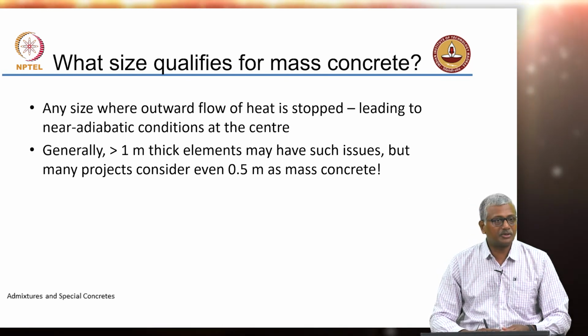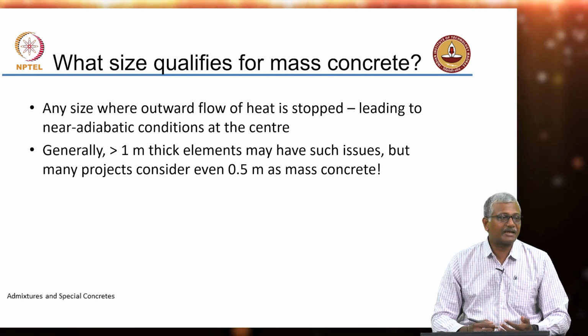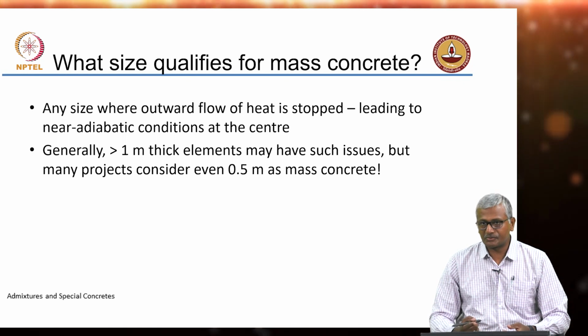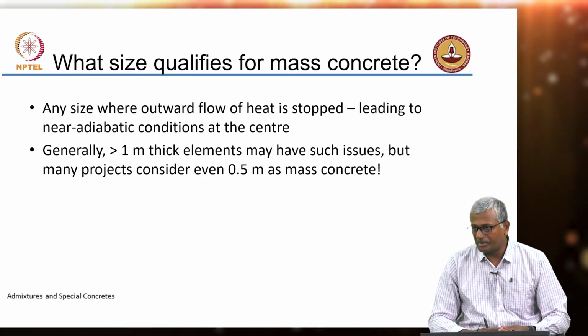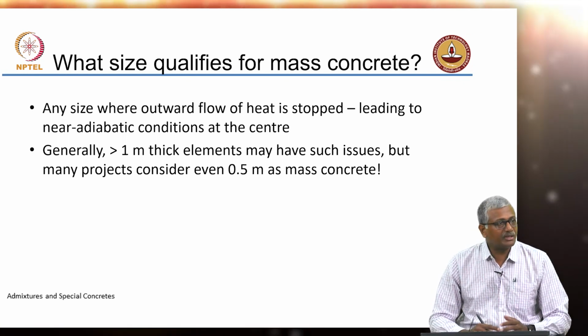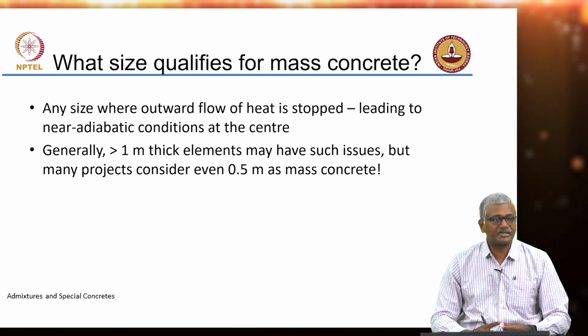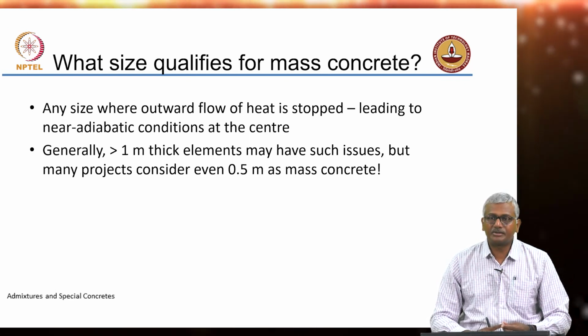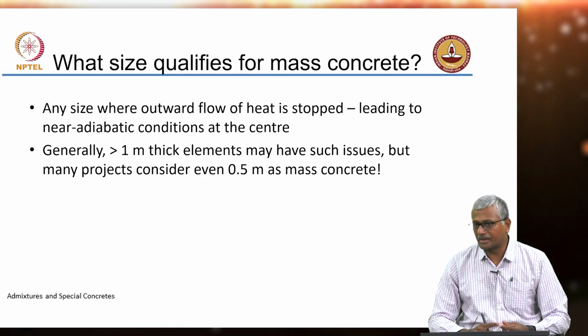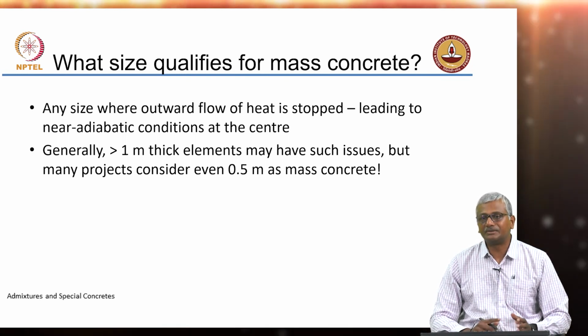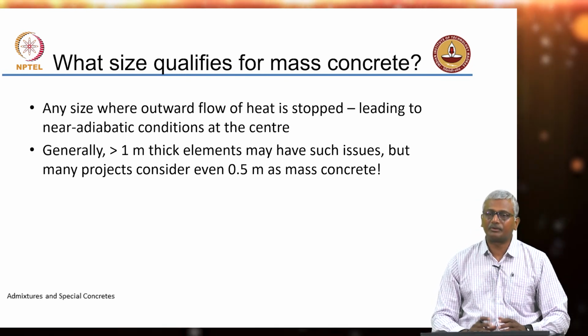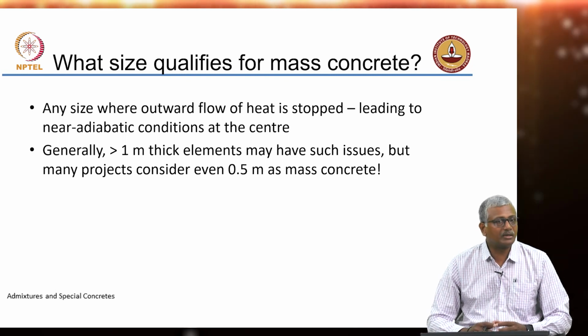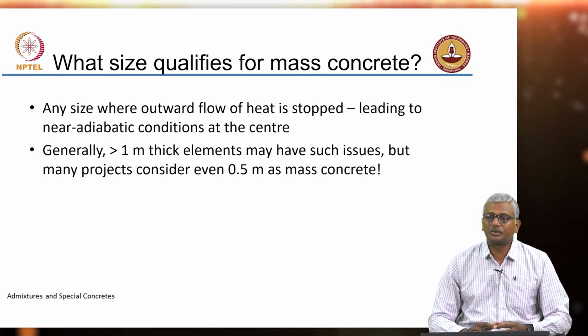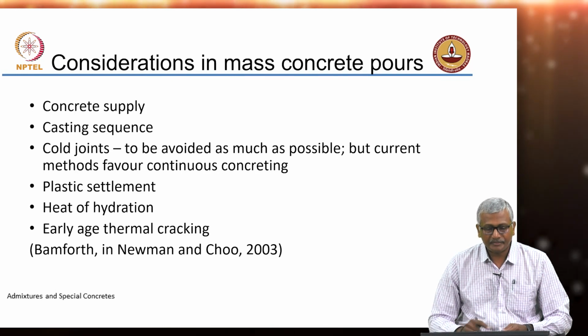So, that is something that you need to remember, that mass concrete effects can be felt even in thinner structures which are just above 0.5 meter. Okay. But most definitely you will feel the effect of the mass concrete heat development in structures that are at least 1 meter thick. Okay. So, you have to ensure that whenever you are dealing with concrete of that thickness, you have to provide special consideration to the temperature effects of mass concrete.